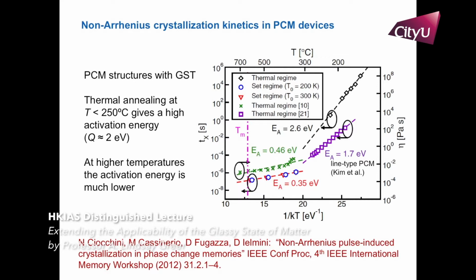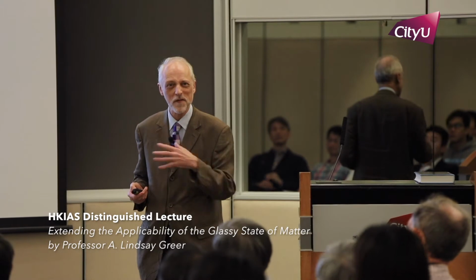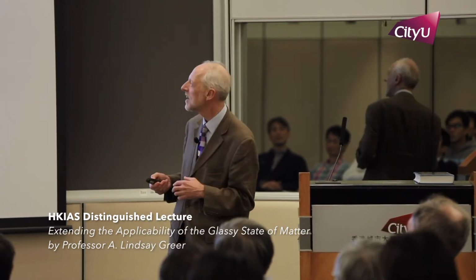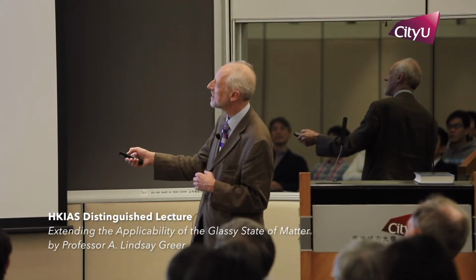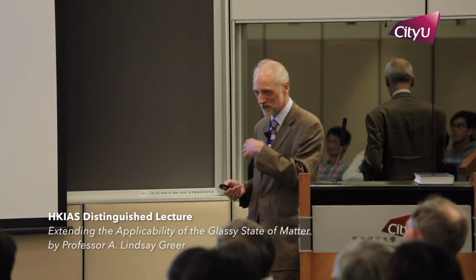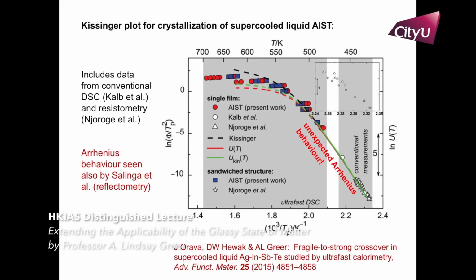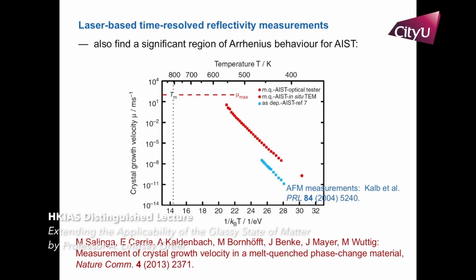It's now fashionable, because of that paper, for the electrical engineers to have given up on the idea that everything is Arrhenius, and they're now prepared to admit that things can be non-Arrhenius in their kinetics, which is really just seeing this range of temperature performance in real devices. There are some systems where, of course, you get bits of curvature, but long bits that are straight. And this was completely unexpected from our calorimetry. And then we were even more surprised to find that it was confirmed by laser measurements, completely different technology.